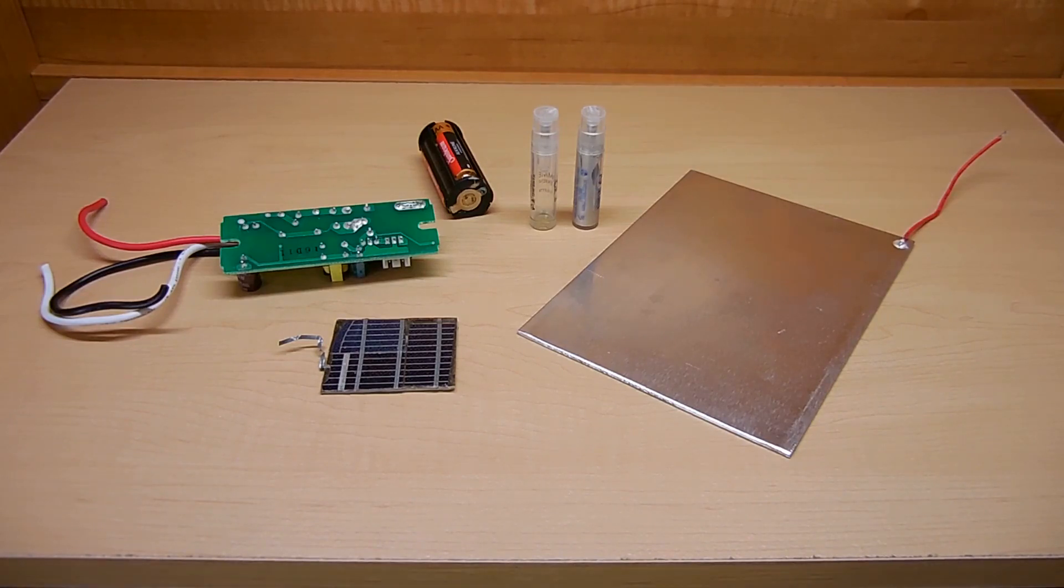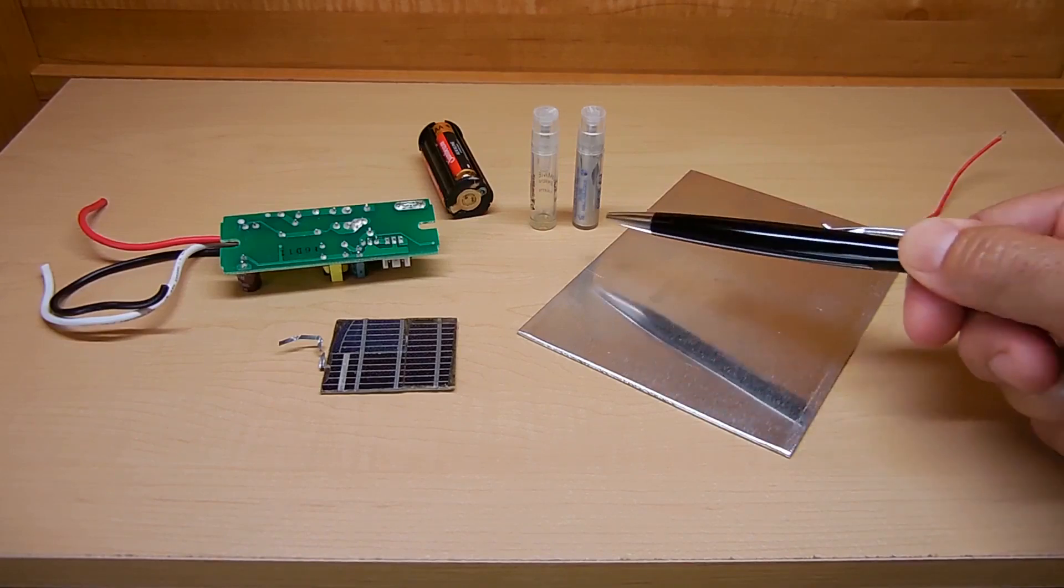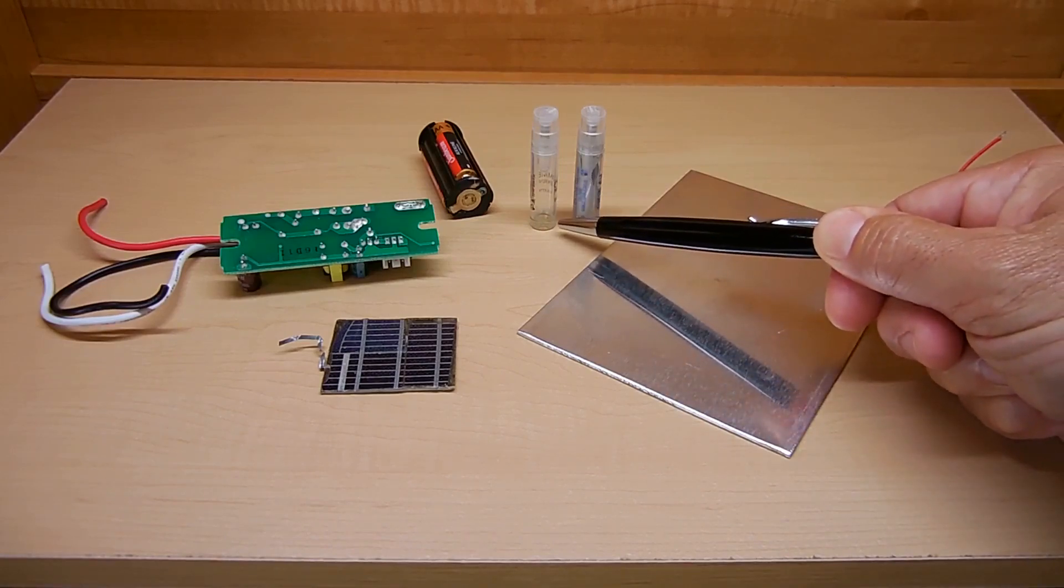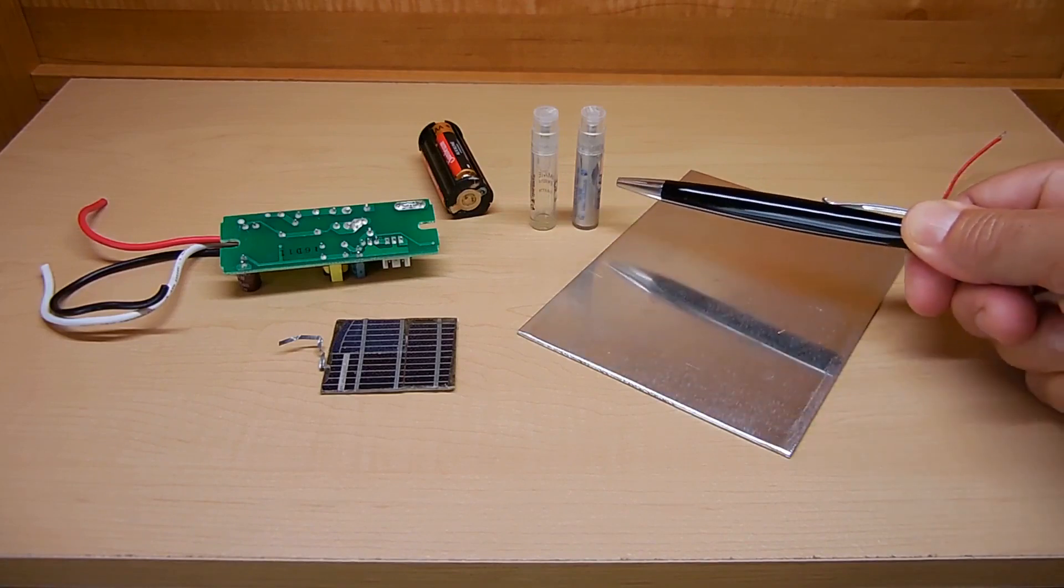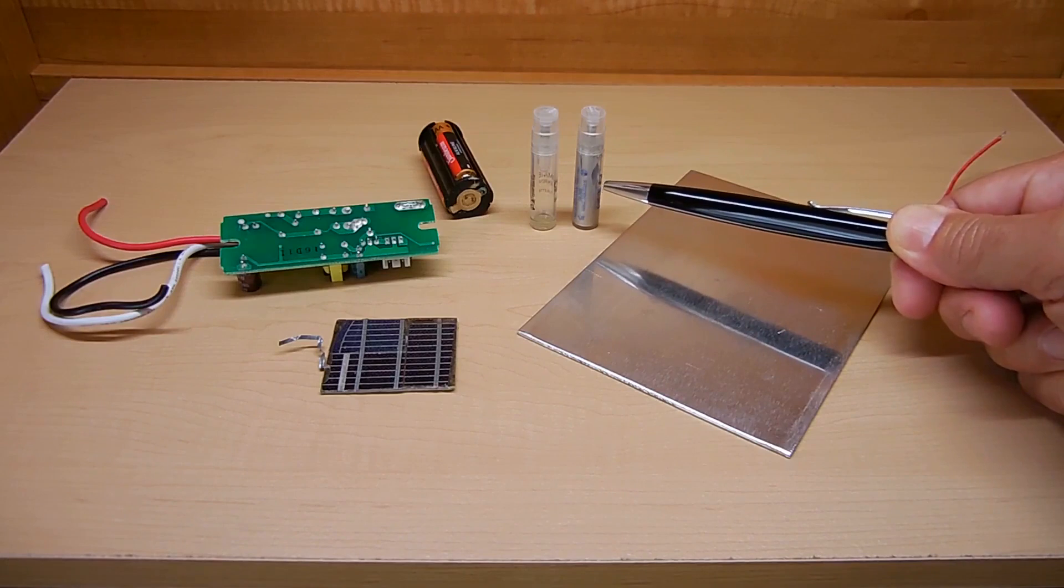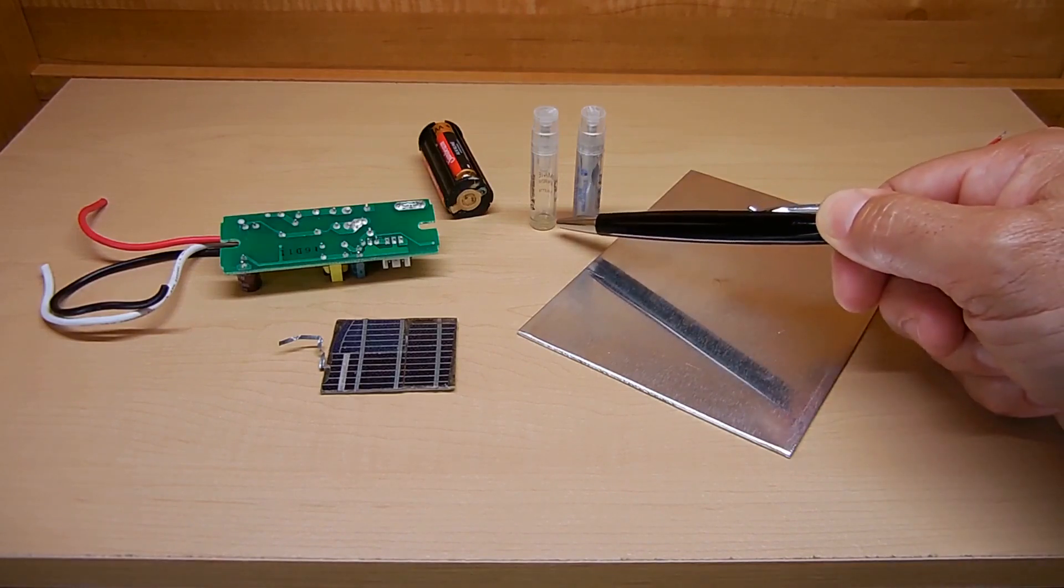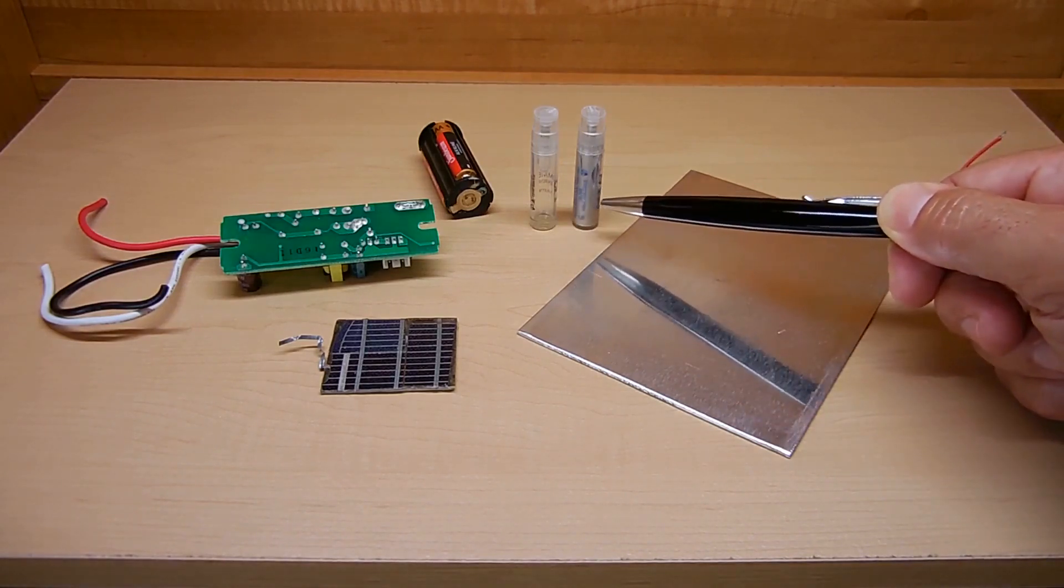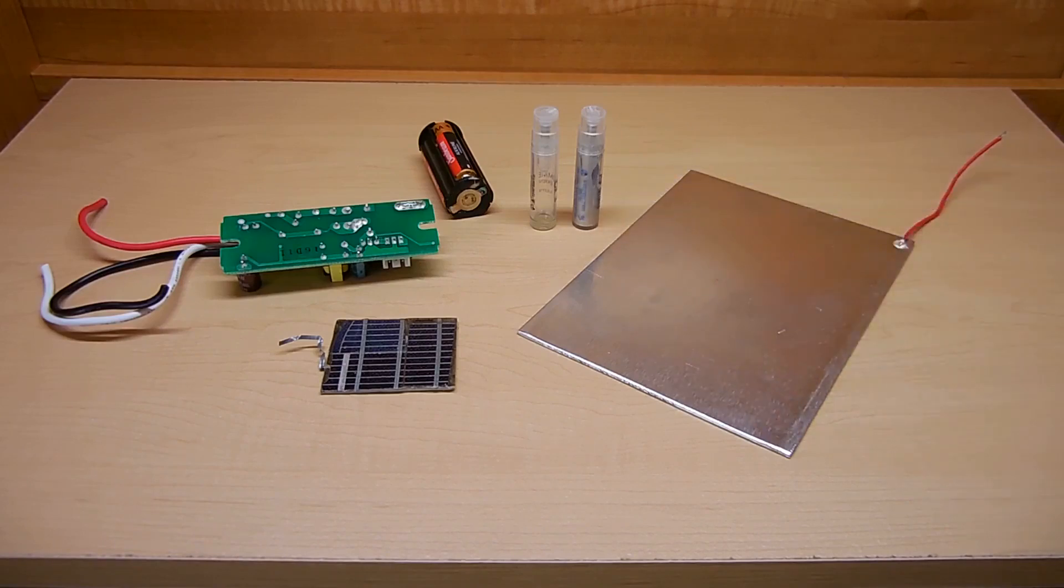around 0.0015 ohms. When you purchase this you can see the activator is an extremely small amount, and the silver epoxy is right up around where the pen is, you would take all the activator, dump it inside of the epoxy right here, thoroughly mix it, and then you would have about 30 minutes to use that before it starts to set up.